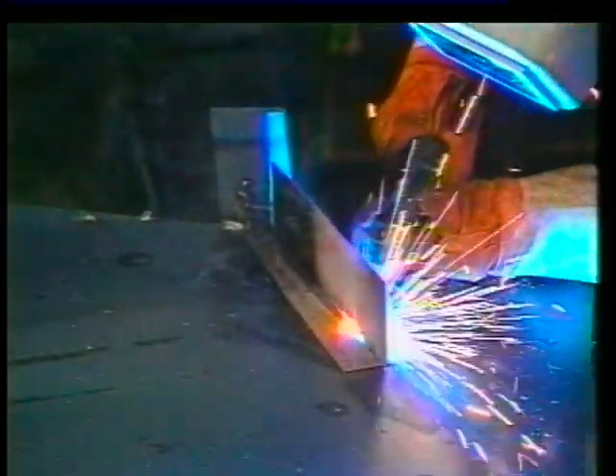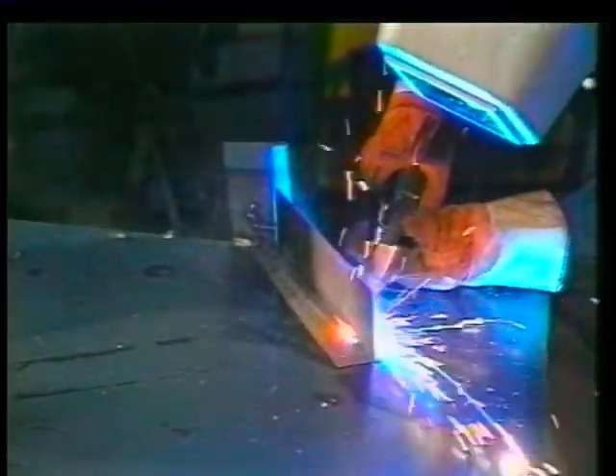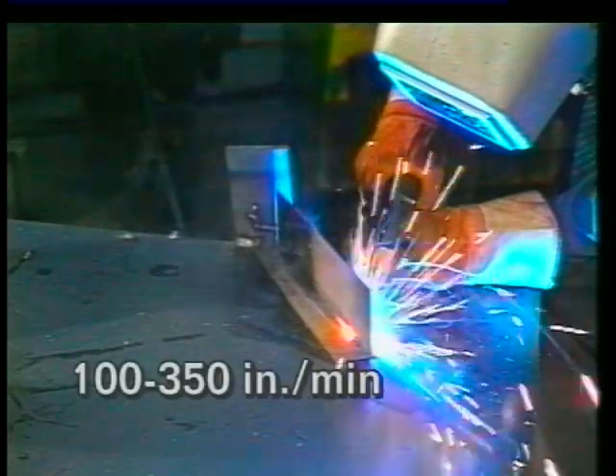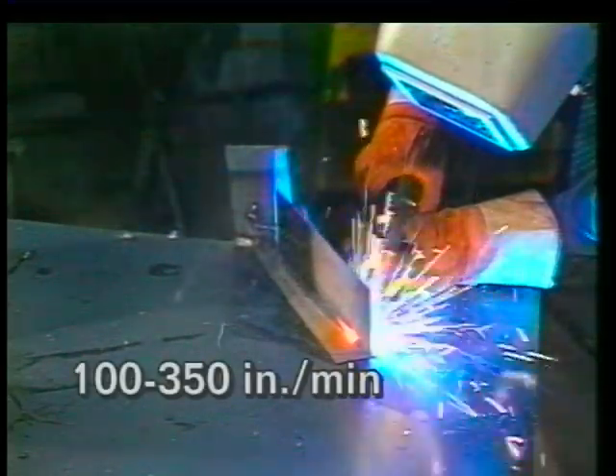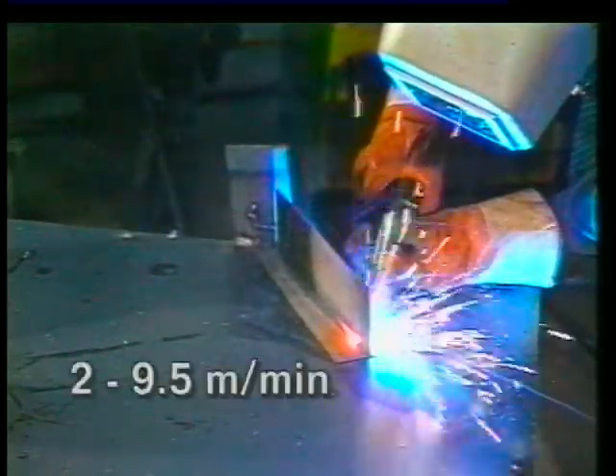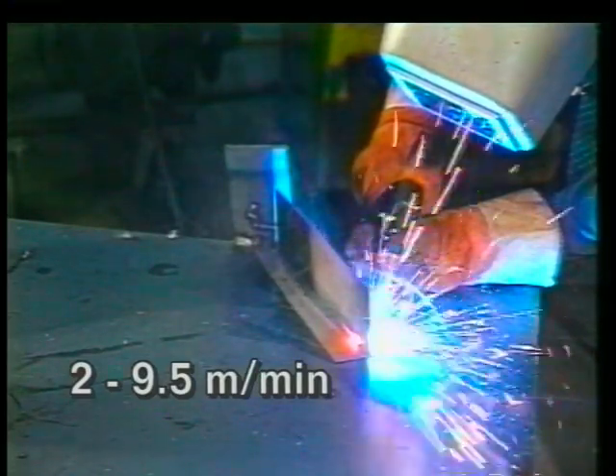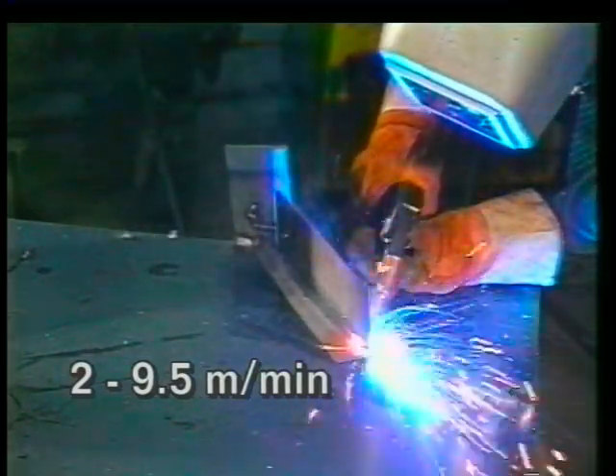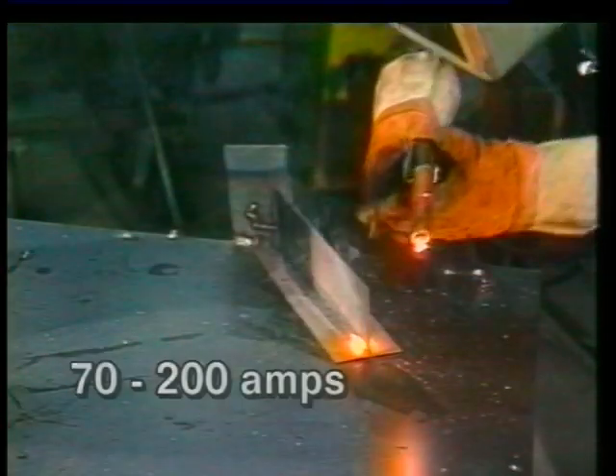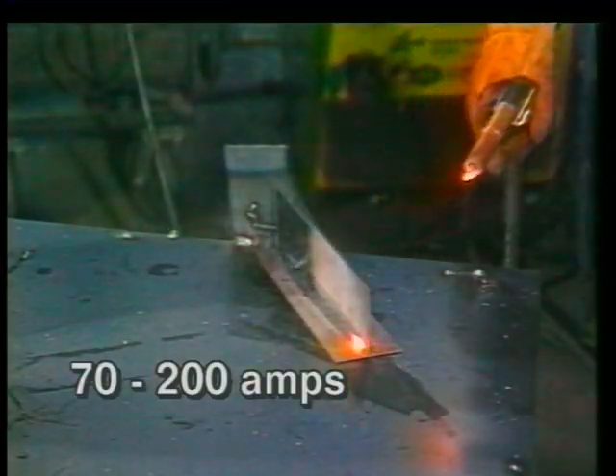With short circuit welding, we have to feed the wire at a typical wire feed rate of 100 to 350 inches a minute. That's 2 meters to 9.5 meters a minute. This will deliver an approximate short circuit current range of 70 to 200 amps.